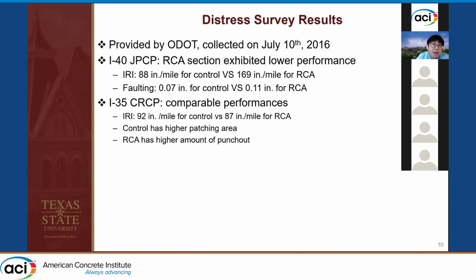We also had a chance to have some distress survey results provided by Oklahoma DOT. The data was collected on July 10th, 2016, about 1 year before we visited the site. And the results were consistent with our field inspection. And for the JPCP RCA section, it had lower performance. It has higher IRI, International Roughness Index. The RCA section was higher than the control. And the RCA concrete also had a higher faulting value compared to the control.